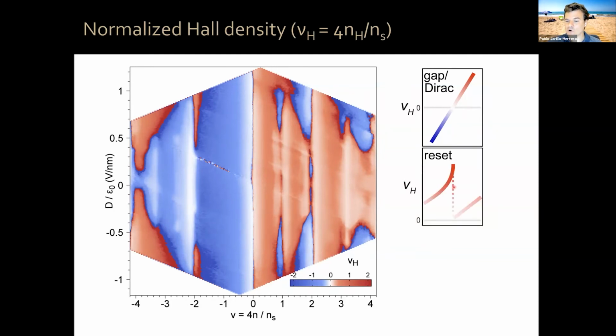So that happens, for example, here across charge neutrality, okay? You can also have a reset of your normalized Hall density, that occurs in those phase transitions that occur at integers, or it can occur there, okay? So you can go from low Hall density to higher, and then a drop near zero, and then it starts growing again. This can happen in red or in blue. Let me show you an example in blue here. You go from light blue to darker blue, and then reset to white, to zero, and then light blue, darker blue, okay? And then you can also have Van Hove singularity type of behavior, where your normalized Hall density flips sign, but diverges before it flips sign, okay? So, for example, you can go from light blue to dark blue, abruptly switch to dark red, and then to light red. And that happens here, for example. Light blue, dark red, light red, okay?